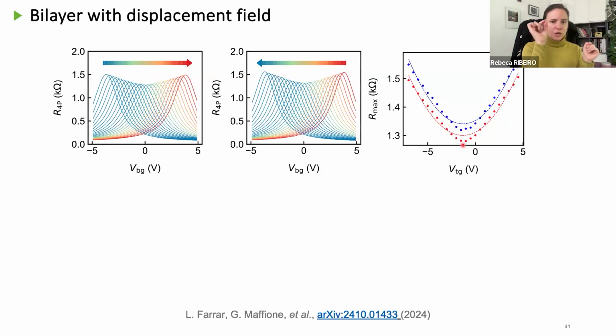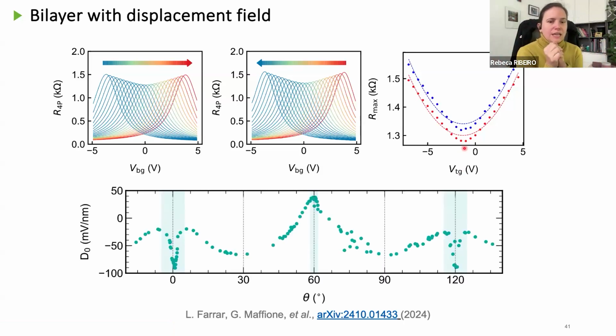If I take that point where the energy gap fully closes for the values of the top gate and the bottom gate, and I extract the displacement field that I told you before, which is the electric field penetrating the material when my charge carrier density is 0, then what I'm gonna obtain is this beautiful curve. I know it's not that intuitive the first time, because what you have to think here is that this displacement field that I'm extracting is in fact how much electric field I should apply to have the closing of the energy gap, which means how much electric field I have to apply to compensate the natural electric field created by the presence of the boron nitride, okay?